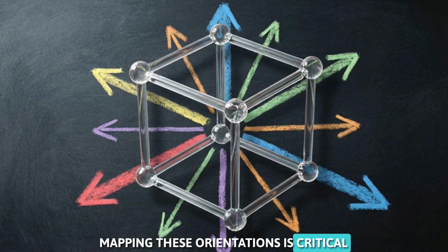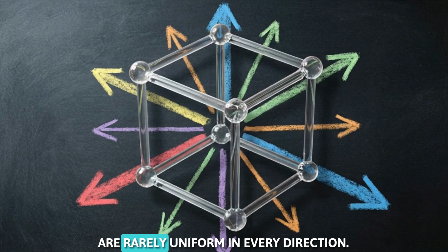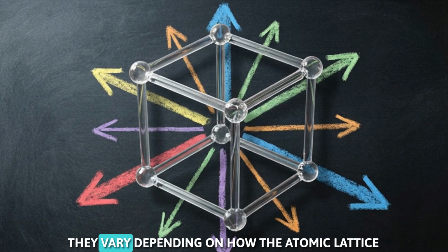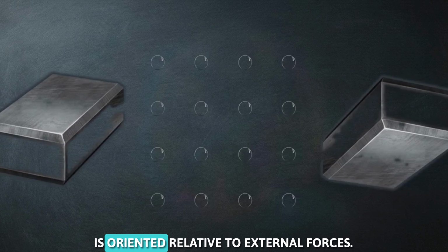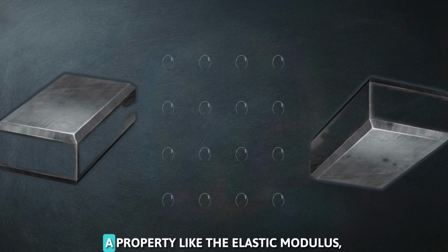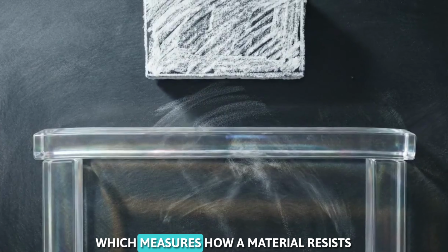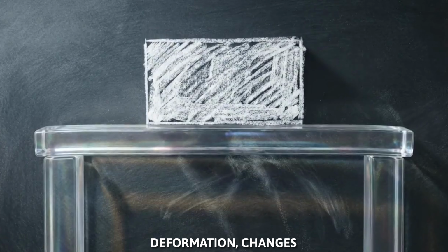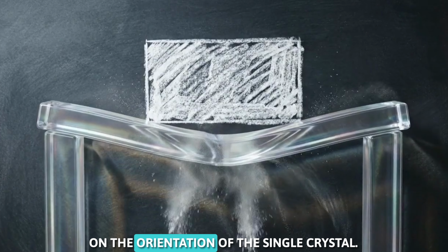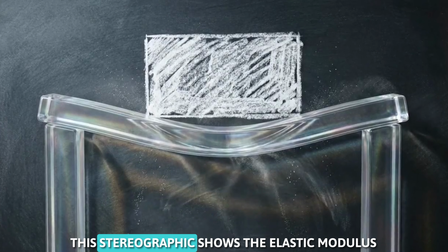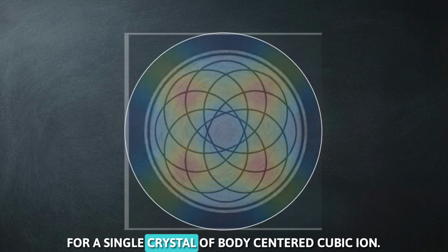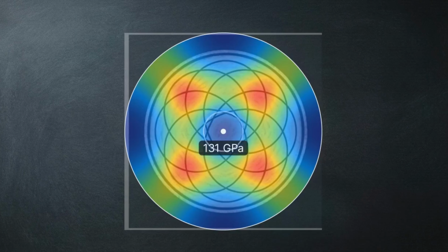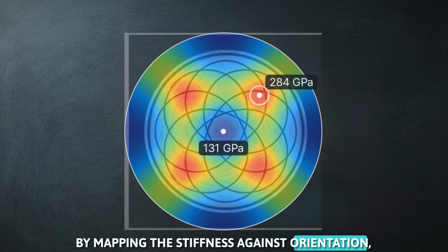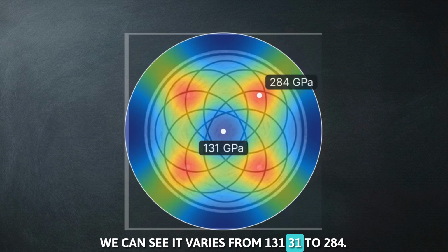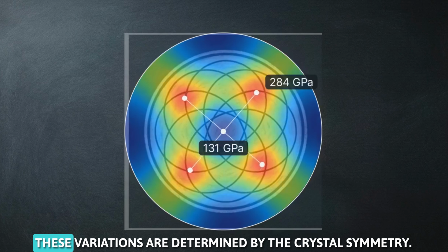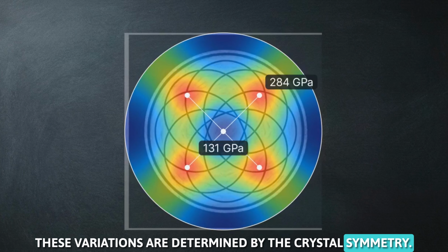Mapping these orientations is critical because the properties of crystals are rarely uniform in every direction. They vary depending on how the atomic lattice is oriented relative to external forces. A property like the elastic modulus, which measures how a material resists deformation, changes significantly depending on the orientation of the single crystal. This stereogram shows the elastic modulus for a single crystal of body-centered cubic iron. By mapping the stiffness against orientation, we can see it varies from 131 gigapascals to 284. These variations are determined by the crystal's symmetry.